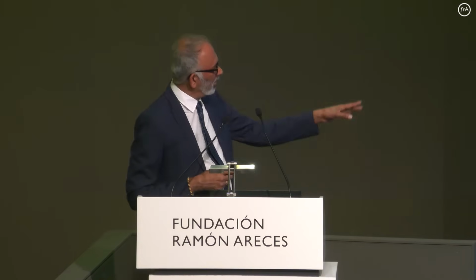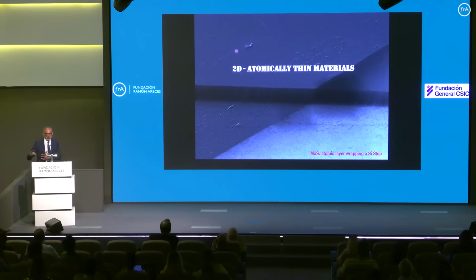And here is an example of a 2D material that has been grown on a substrate and transferred onto another substrate. And you can see that the structure already has a lot of extrinsic defects that appear as I transferred it to a different substrate. And you can imagine, a material that is as thin as a single atom and pretty large in lateral size, you're trying to pick it up and place it onto the substrate. For anybody, that would be a tremendous problem. And, of course, because structure and properties are so strongly correlated, you do see the effects of that in the materials that you deal with.